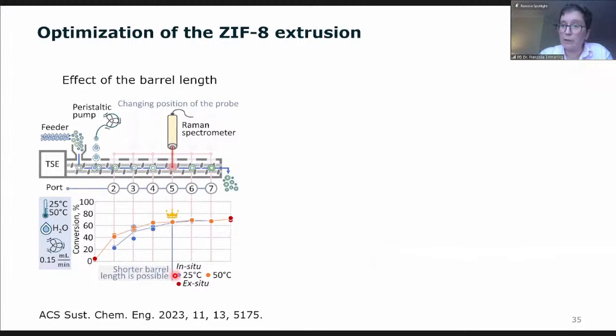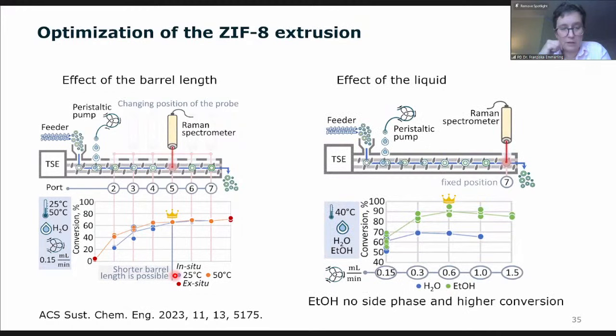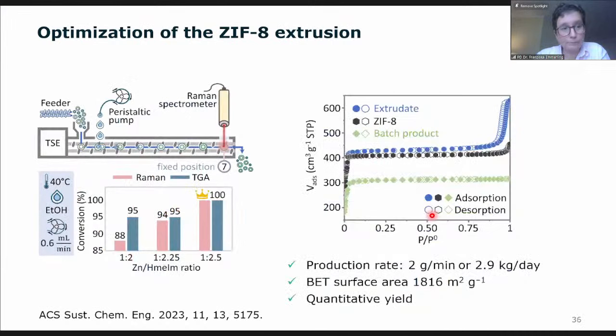In the next step, we changed liquid from water to ethanol, and you can see it's now even better. And we also found some ideas on the feeding rate. And then we experimented a bit more with a linker to metal ratio, and then found the optimal conditions. And you see here the final product. So that is in black again, the commercial one, and in blue, our product. So, and that is really a good comparison. And now we have a process where we can produce up to 3 kilograms per day, which is quite good for scaling up from a milligram process.